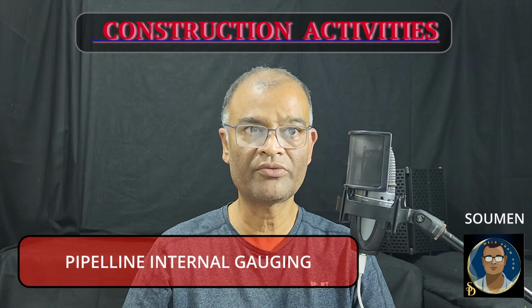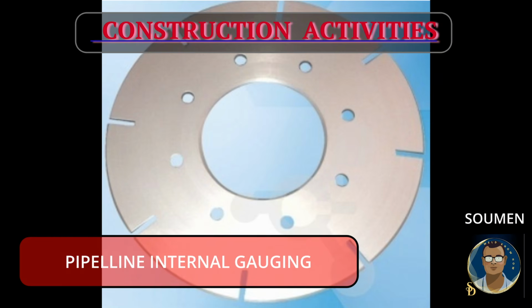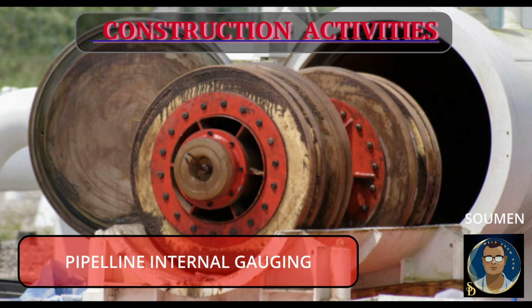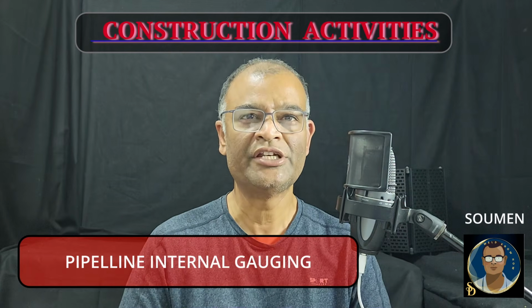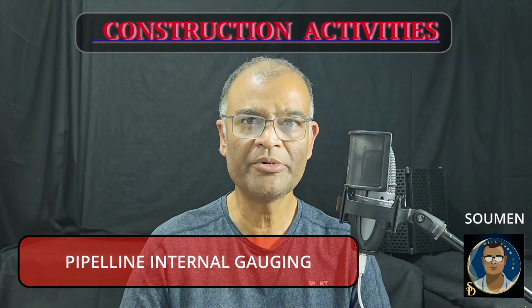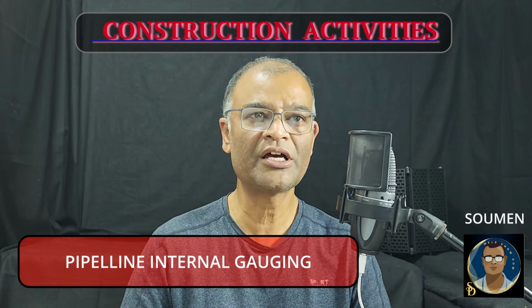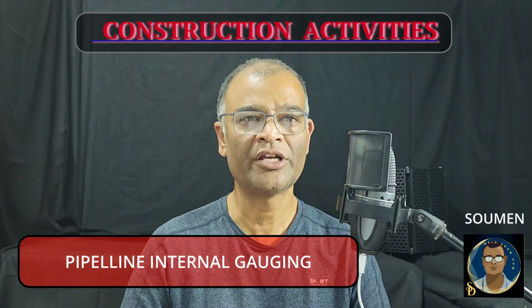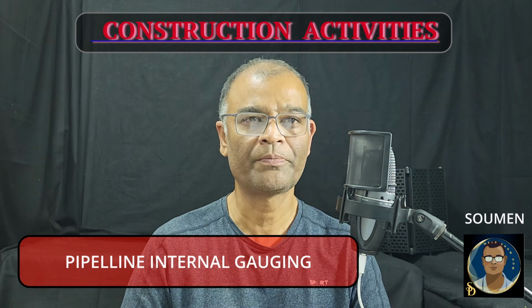Internal gauging is also done for the bare pipeline, I mean internally not coated, to check the pipe diameter is not deviating beyond the tolerance anywhere. One aluminum gauging plate is put with the scraper, which is 90 to 95% of the internal diameter of the pipeline. If there is any damage to this gauging plate when it comes out from the line, then the damage is measured. If it is beyond the limit or the tolerance, then an investigation must be done to find out any dent or any external damage to the pipeline.